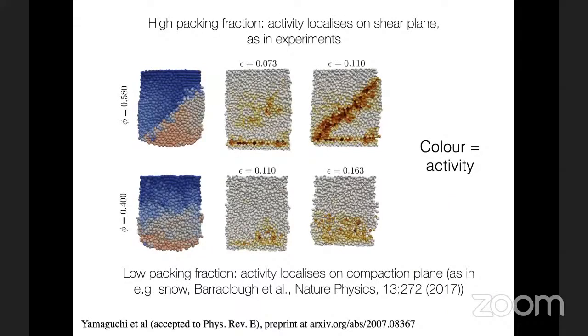This is just another mention of the compaction band. If you look at where the activity is localized, the activity is represented by color here, and we go from a transition at high volume fraction from a shear band to a compression band at low volume fraction. This relates to some work, for example, from a group in Erlangen on snow, which was published a few years ago in Nature Physics. It's similar also to work Pedro Reis did on the compressive failure of foams, which fail in a similar way.